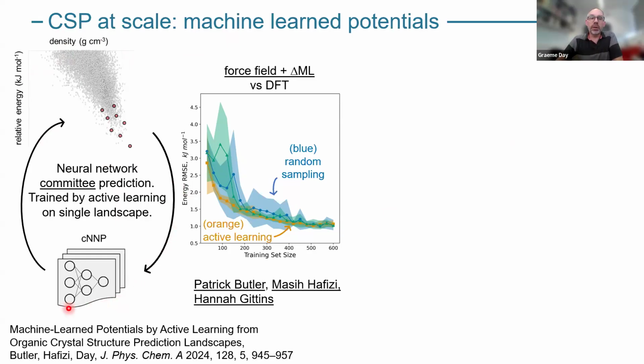Okay. And then we can train machine learning models. Here, we were using a committee of neural networks, and we train that to learn the energies or the relative energies of these structures. Okay. What we are actually learning in this work that we published just last year was a correction to the force field. So we're not learning the absolute lattice energies, but we're learning where there are errors in the force field when compared to density functional theory. And it turns out that with just a small number of training points, you can start to really reduce those errors in a baseline force field.